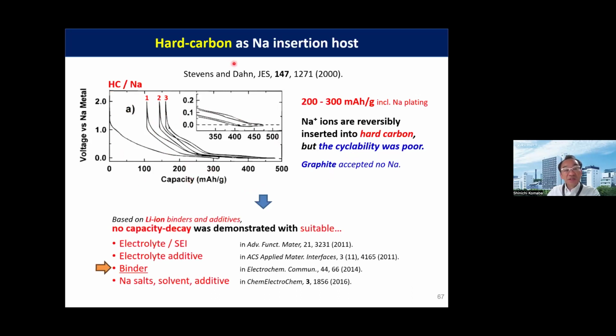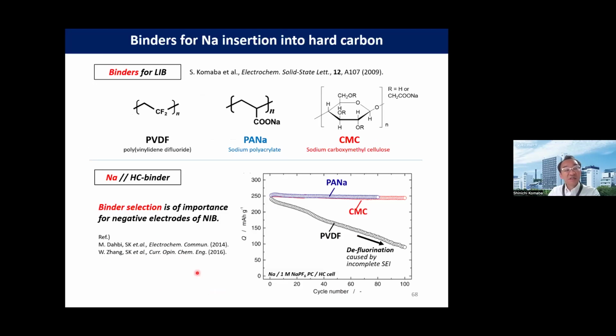So based on this very pioneering paper, we tried to optimize the electrolyte/SEI, electrolyte additive, binder, sodium salt, solvent, and additive. And one of the examples is that the binder is very, very important. And it was very fortunate that we had reported 3 different binders for lithium-ion batteries. And by using these binders for the hard carbon electrode in a sodium cell, you can see here that polyacrylate and carboxymethyl cellulose are the best choice compared to PVDF.